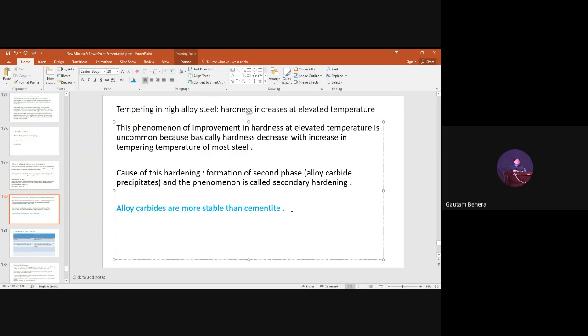But just the opposite, if we have carbides, nitrides, right? Oxides, forget about oxides, they are insoluble basically. But if you have carbide or nitride precipitates, they are basically stable even at high temperature. You can go to 1000 degrees centigrade. Sometimes if you have niobium carbides, vanadium carbides, you can go to 1200 degrees centigrade. Those carbides are stable even at 1200 degrees centigrade. They will not dissolve in the matrix, right? So that's why they provide strengthening. That is the reason why hardness increases upon tempering at elevated temperature, right?